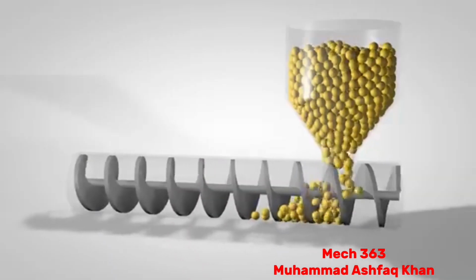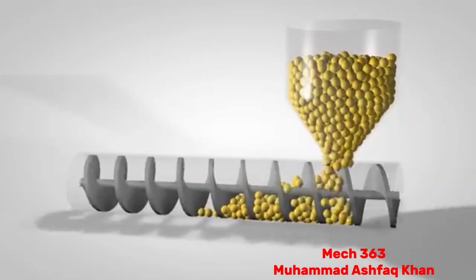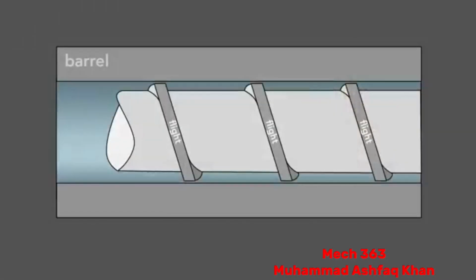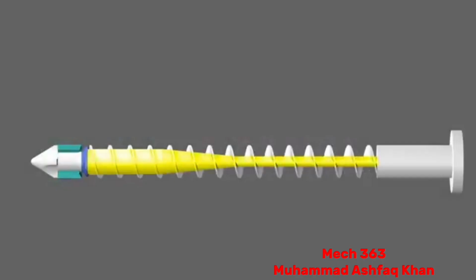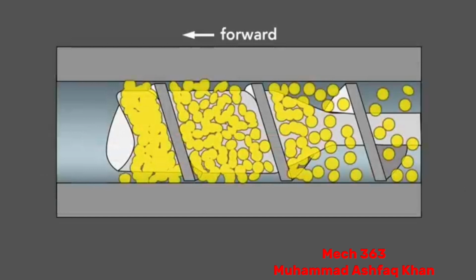As the screw rotates, the flights transport the raw material forward through the barrel. The flights also serve to mix the plastic. The screw action agitates the melting pellets within the flights to create a uniform mixture. The shaft's diameter increases along the screw so that the distance between the wall and the shaft decreases. The flights then squeeze out air as they move the plastic forward, and they shear the pellets and press them against the barrel's wall. This shearing creates friction and so heats the plastic throughout.